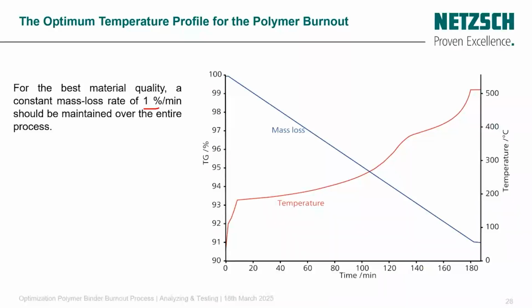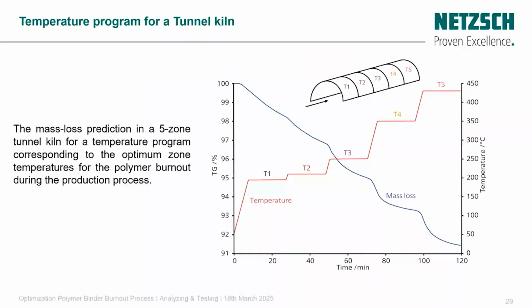And in this case, we choose the 1% mass loss per minute to obtain the best material quality while reducing the process time. Also, as shown here, we can also use the multiple step prediction option in our Kinetics Neo software to provide you with the temperature program at different holding stages, or at 5 holding stages as shown in the tunnel kiln example.